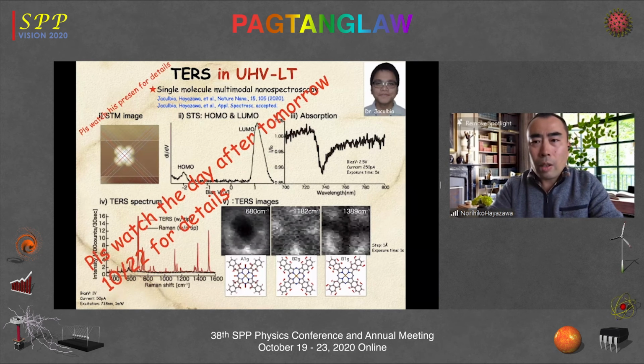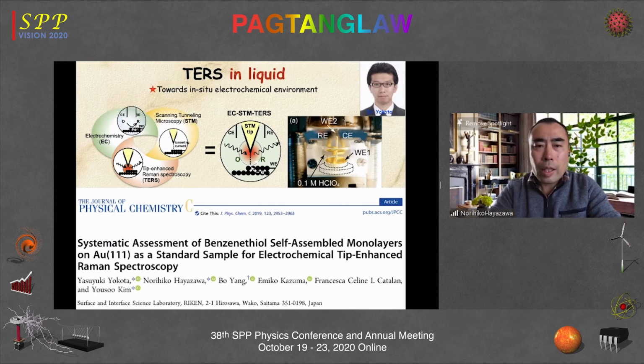And in addition to ambient and ultra-high vacuum low temperature, we are also extending our work, tip-enhanced Raman spectroscopy, to liquid environment, especially towards in situ electrochemical environment. So it's inside the liquid. Working with my colleague, Dr. Yokota, we have designed a unique electrochemical cell like here, employing 4 electrodes, including 2 working electrodes. The tip and sample also work as working electrodes in the electrochemical system, so that you can precisely control the potential of tip and the substrate relative to the reference electrode here.